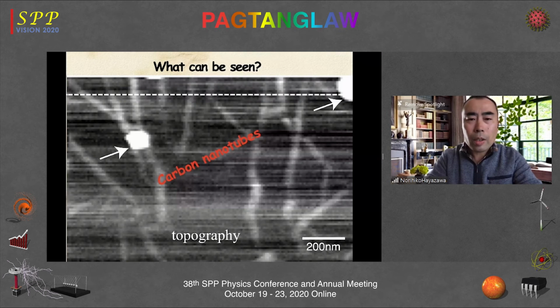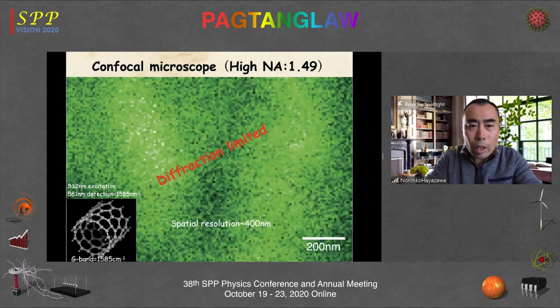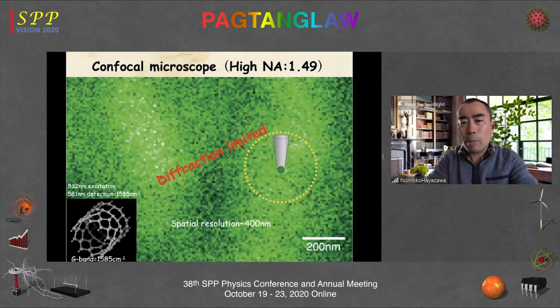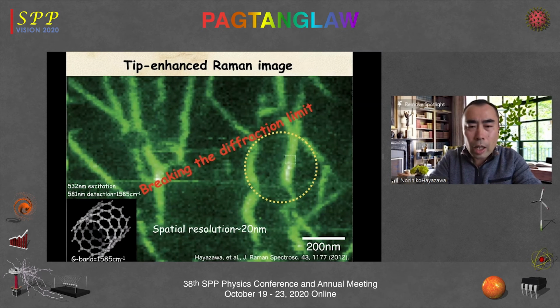What can be seen by this technique, for example, is here, carbon nanotubes dispersed on the cover slip. You can see lots of carbon nanotubes by AFM topography here. This is the AFM topography. But when you employ a conventional confocal Raman microscope using a lens, because of the diffraction limited focus spot size like this, you cannot spatially resolve each carbon nanotube. So in the case of tip-enhanced Raman spectroscopy, what you need to do is to bring the tip onto the diffraction limited focus spot and generate the nanoscale light source like here and scan over the sample so that you can clearly visualize each carbon nanotube spatially like here. In this case, we achieve a spatial resolution of up to 20 nanometers.